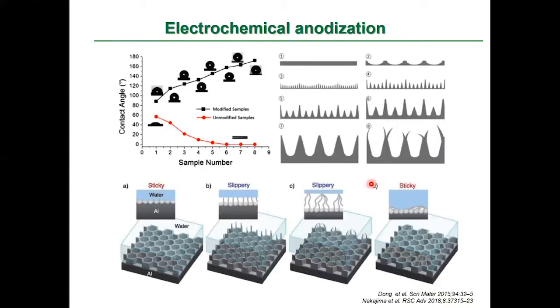So this is another example where titanium surfaces with different morphology. See the surface morphology, depending upon the surface morphology, the contact angle varies. And we can make either sticky or slippery superhydrophobicity, that is, a superhydrophobicity with self-cleaning or not. And we can make that by adjusting the anodization conditions.